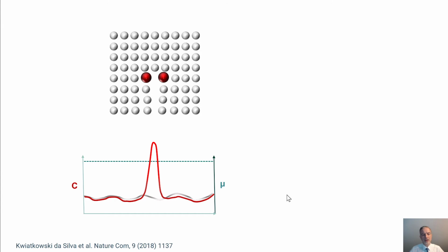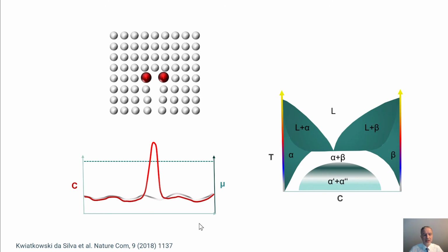And we all know in global thermodynamics, such a dislocation as a defect would not exist. But if it does exist, if it's so to say thermodynamically frozen in, then you have an equilibrium segregation that gives you a new concentration working point, which is now here and not here where you expect it for the global equilibrium. And if you translate that now into the phase diagram, and of course only here into a bulk